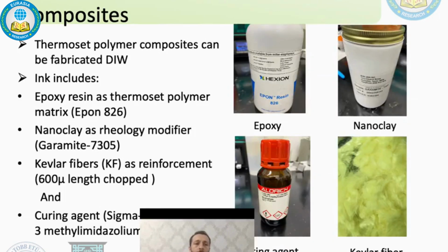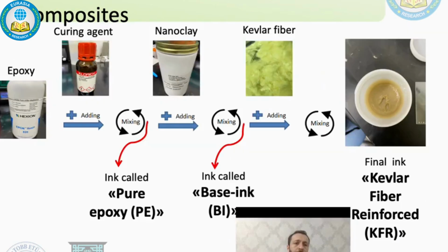Ink for thermoset polymer composites. Thermoset polymer composites can be fabricated with direct ink writing, but the first stage of printing a thermoset polymer composite is to prepare a printable ink. A printable ink includes epoxy resin as a thermoset polymer matrix and nanoclay as a rheology modifier. Rheology modifier has a crucial role in preparing ink because ink viscosity has a crucial role in direct ink writing. To get a printable ink, ink viscosity must be adjusted carefully via rheology modifiers. And as a reinforcement, we use Kevlar fibers. And lastly, curing agent to complete the thermal curing process.